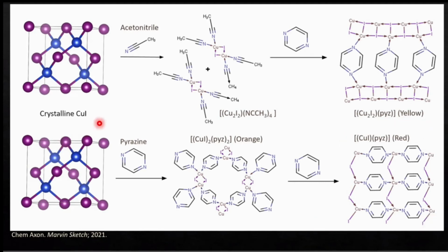And so what's interesting about this is that it presents us with an interesting conclusion. So in water, the primary path is going to be going to red, or orange and then to red, while in acetonitrile solution synthesis, you're going to go through the mobile dimer phase and then to the yellow polymorph. But then if you are in acetonitrile-assisted accelerated aging, then both of these pathways are available. The acetonitrile could solvate the copper iodide, but the pyrazine is in much higher relative concentration to the acetonitrile whenever you're using 45 microliters of acetonitrile. And so the pyrazine pathway is the one that's going to take over, and the orange and then red are going to be shown rather than this yellow pathway.